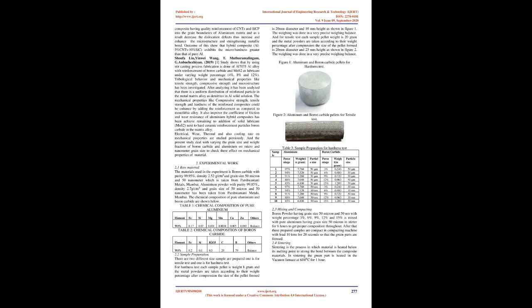4. KK Saravanan, S. Mahendran's article deals with aluminium 6082 alloy mixed with boron carbide reinforcement material by the mechanical stirring method. The specimen is tested by hardness and tensile tests. The SEM analysis is made and calculates the grain particle distribution. These castings are machined in CNC machines. The machining parameters speed, feed, depth of cut and all types of inserts are studied. These machinability studies are compared with mono-alloy and composite materials. The machinability values are higher for composite material than monolithic alloy.